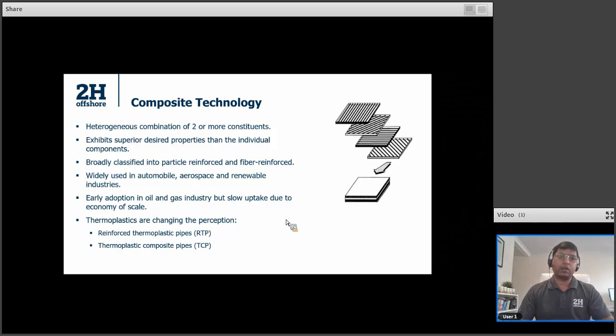Primarily, we can classify the composite pipes into two categories. The first is reinforced thermoplastic pipes, where the composite layers are loosely bonded on top of the liner and then held on with a jacket structure. So this is not a bonded structure, and because the composite layers are loosely wrapped around the liner, the pressure rating for such pipes is quite low, and hence the reinforced thermoplastics are primarily used in land-based applications. Thermoplastic composite or TCP pipes is another variation where the composite, the liner, and a protective layer, if you want, can be fused together and increase the resistance and strength of the structure. So this enables us to perform in a more challenging environment.